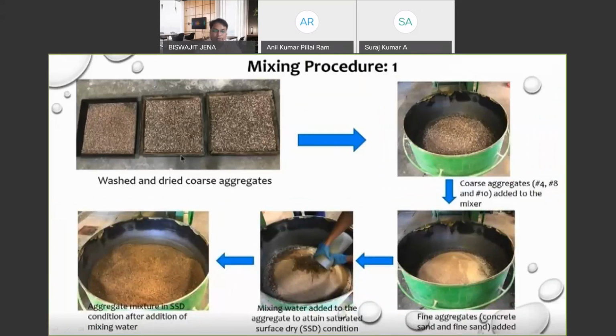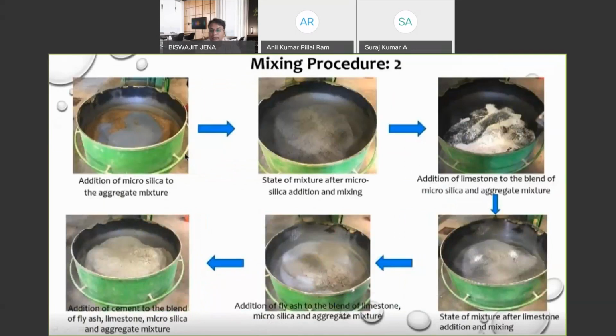Add silica fume first. Silica fume is added first to break down the silica fume agglomerates. So you put the silica fume in and make the silica fume dispersed by mixing, and then add the limestone, because limestone is the next larger size. Then you mix this well so that you get a good mix, and then add fly ash.